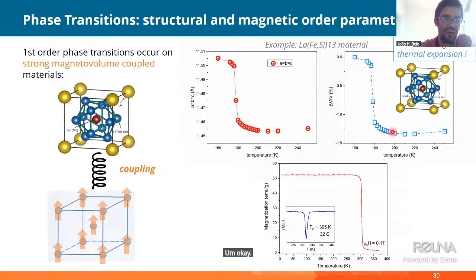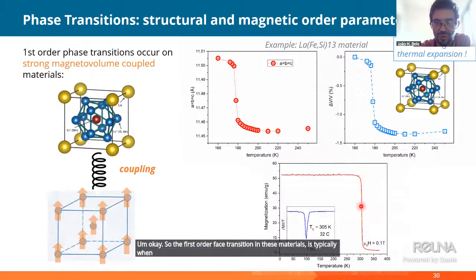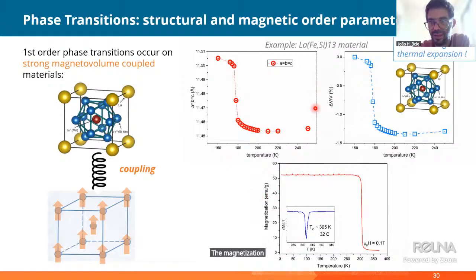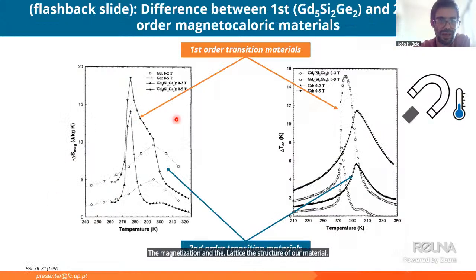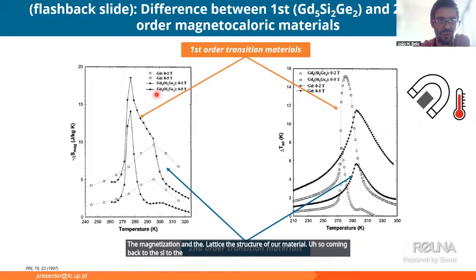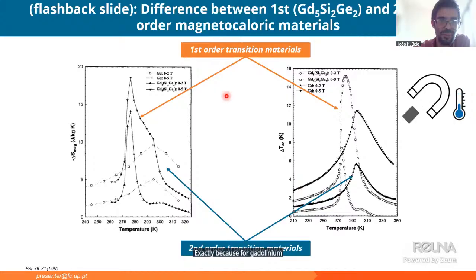Okay, so a first order phase transition in these materials is typically when there is a coupled or nearly coupled transition between the magnetization and the lattice, the structure of our material. So coming back to the graphs that I showed you before, we see that for the gadolinium silicon germanium alloy, the effect is larger than for gadolinium, exactly because for the gadolinium silicon germanium alloy we have a first order phase transition, in contrast with the second order phase transition presented by gadolinium alone.